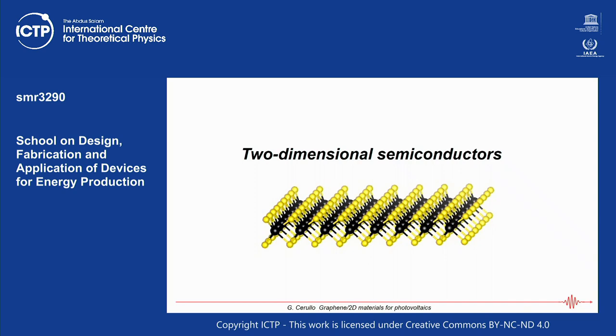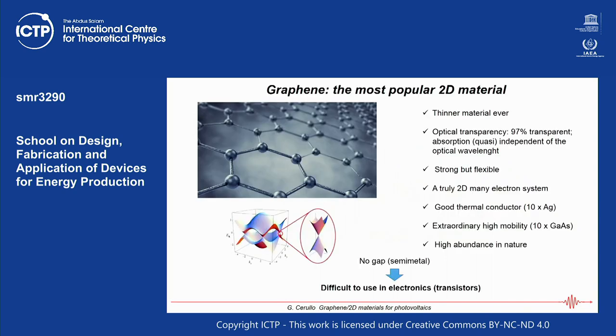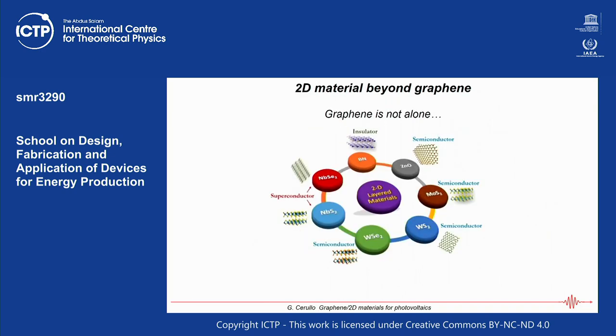Graphene was just the beginning of the whole field of two-dimensional materials. While it has many excellent properties — thinnest material, transparent yet conductive, absorption quasi-independent of wavelength, strong but flexible, high thermal conductivity, high electron mobility, and made of abundant carbon — it is not a semiconductor; it is a semi-metal. This makes it difficult to use graphene in electronics, which is based on semiconductors. Soon after 2004 it was realized that many materials can be exfoliated just like graphene to become atomically thin two-dimensional materials.